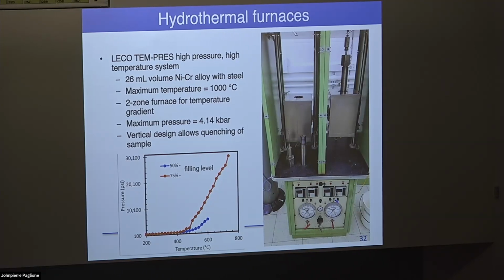You basically set up a zone where all your constituents will dissolve. And then you have another zone at some temperature where the quartz will start to fall out of the solution, depending on the chemical potential or whatever you're tuning. So in those 2 zones, you have dissolution. It's essentially the same sort of thing as CVT. You have dissolution in one zone, it transports to the other zone based on convection. And as it goes to the other zone, it falls out of solution and deposits on the crystal, and you get slow crystal growth. So that picture I showed of those really large quartz crystals, that's how they grow.